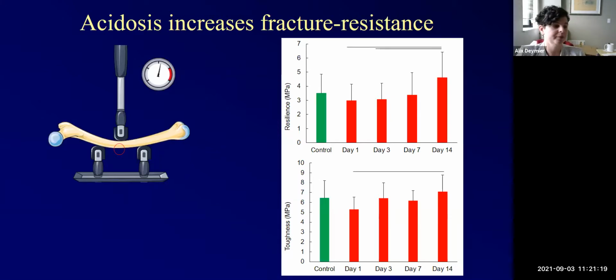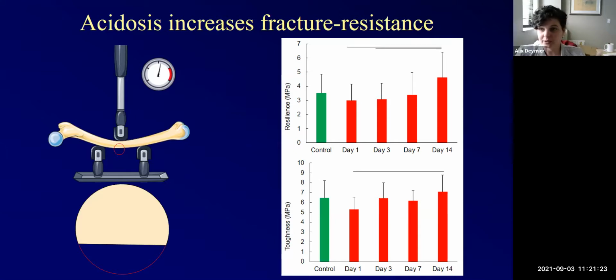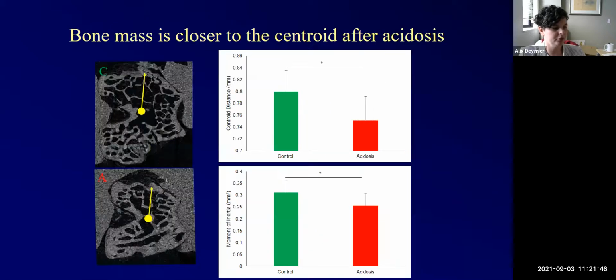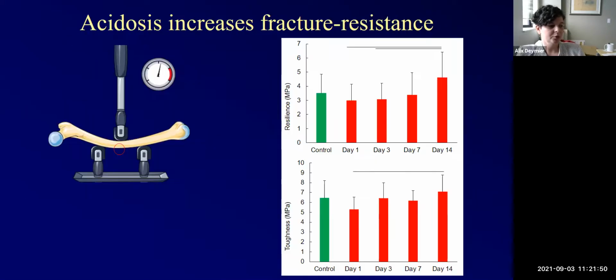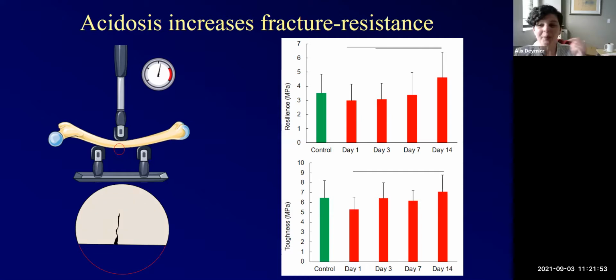Well, our theory at this point is that your initial bone had a certain mineral composition and a certain amount of mineral. But remember, we saw that the inside of the bone actually had a reduction in mineral to matrix. That means that our composite, you're taking out the stiff reinforcement of ceramic and you're leaving behind a much more polymeric proteinaceous structure. So if I have a crack propagating through that material, it is going to encounter a much more plastic material, which can have the formation of a plastic zone at the crack tip, and therefore you're less likely to fail. So this is our theory at this point.